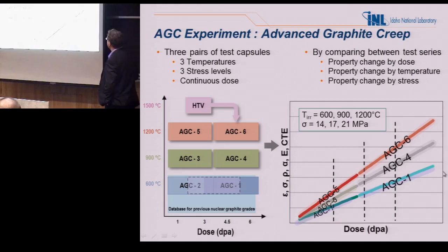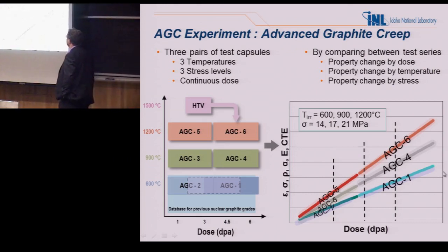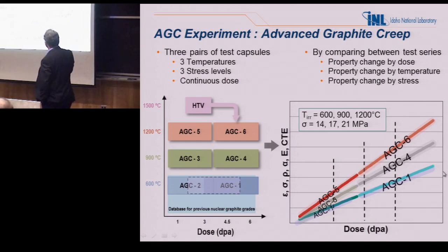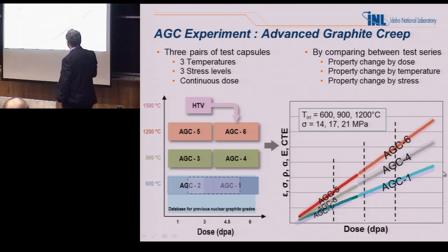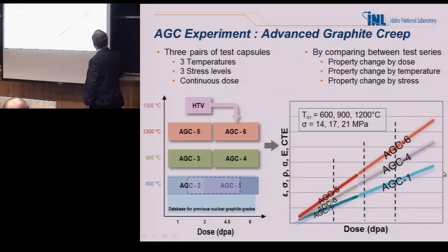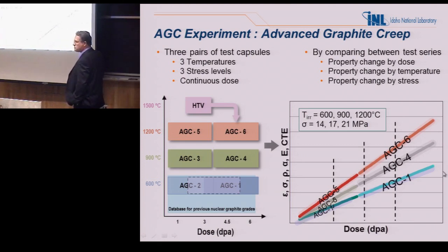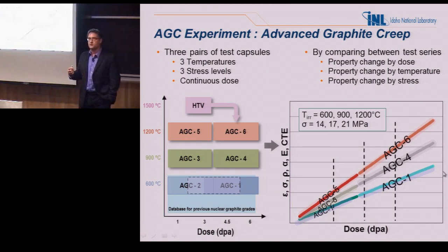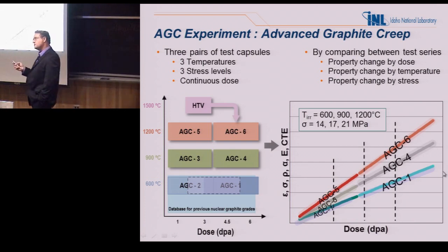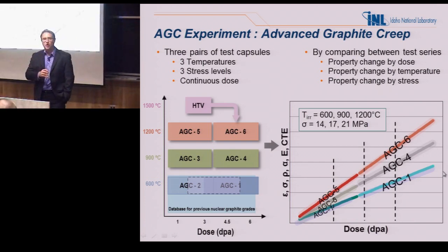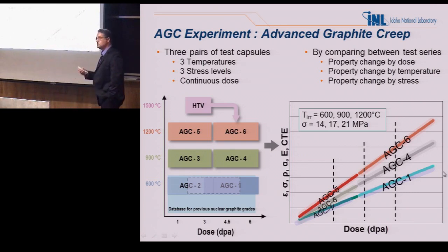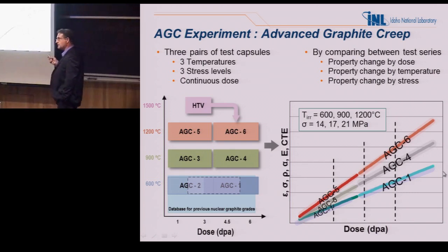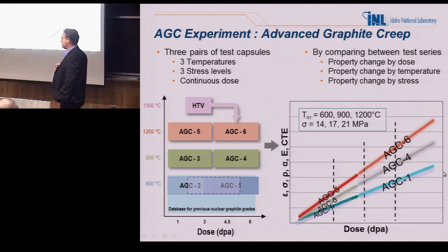So this is my project. The Advanced Graphite Creep Experiment. 3 pairs of test capsules at 3 temperatures, 3 stresses, and over a continuous dose. Each one of these holds about 500 samples, so we're talking about 3,000 samples, which is about the sum total of all the creep specimens that's ever been done historically. So it's a huge, huge effort by the United States to put a stake in the heart of this problem once and for all.